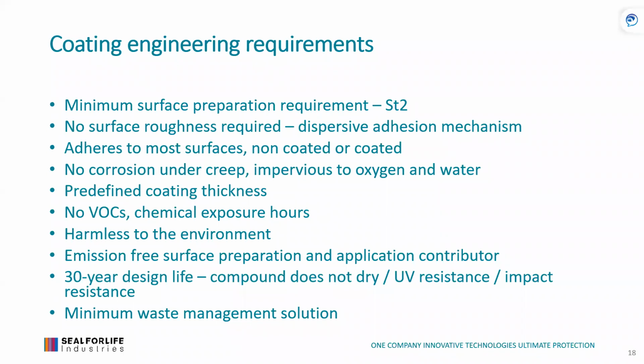No surface roughness, that's what I mean. Adhering to most surfaces, so not only the steel, but also coated or healthy coatings that are there. No corrosion under creep, so you don't want water to go underneath it, or you don't want corrosion when it's expanding. I think the rule was times 10: 1 micron is 10 microns, 10, 100, and then it pops the coatings off. No VOCs, harmless to the people, to the environment, etc.